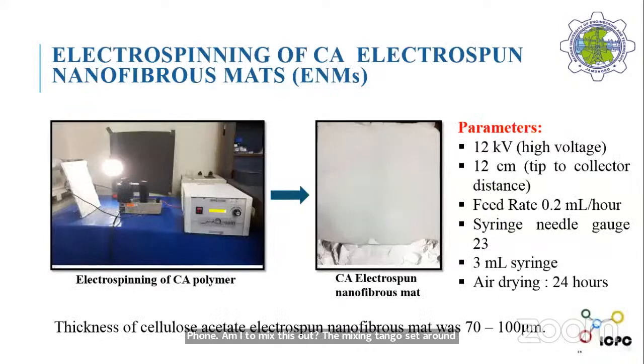After making the polymer solution, we moved to the electrospinning process to make nanofibrous mats from the CA polymer. During electrospinning, 12 kV high voltage was set, the 12 centimeter distance from tip to collector was fixed, and the feed rate was 0.2 ml per hour. The syringe which I use is needle gauge 23 and a 3 ml syringe. After making the nanofibrous mats, I air dried them for 24 hours to remove the extra residue.